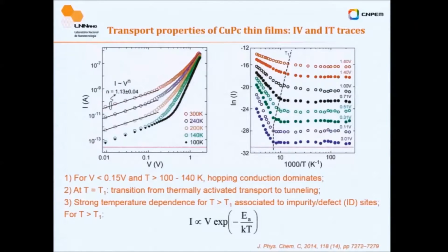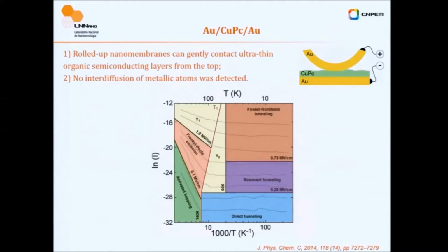I also did a lot of electrical characterization. You can see a crossover between a thermoactivated process and tunneling. You figure out a lot of figures of merit here, and you also manage to draw a map of my structure. That is the final figure of this paper, where you can simply map, as a function of electric field and temperature, which kind of transport mechanism we have.